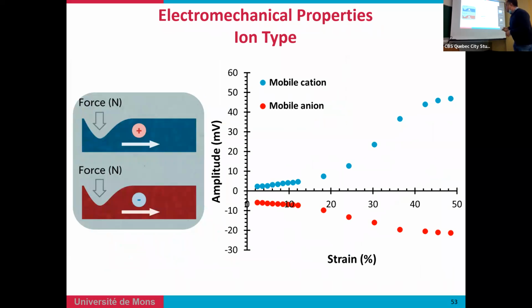To show that, we took a gel containing a mobile cation and a mobile anion. You can see, based on the difference of charge and using electrodes, that in the case of the mobile cation, when you press, you have an amplitude that is positive.